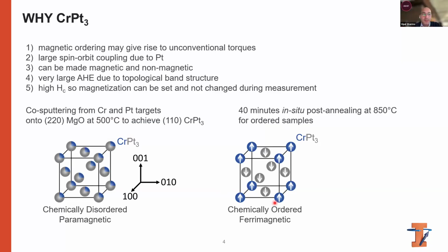Have you measured any surface roughness after 850 degrees Celsius? If the surface is good even at 500 and 850, then I believe it's good. But in my experience, such high temperature generally degrades surface morphology, making it very rough, and interface properties will be severely degraded. I think the roughness is relatively good in both cases, because the properties of the film are good, and we also grow a relatively thin copper layer on top of this, and we see no effect of magnetism from the chromium platinum 3 on the ferromagnet. So I would assume there are no pinholes due to roughness in the copper. We did measure the roughness and it's not extraordinary, or very high.